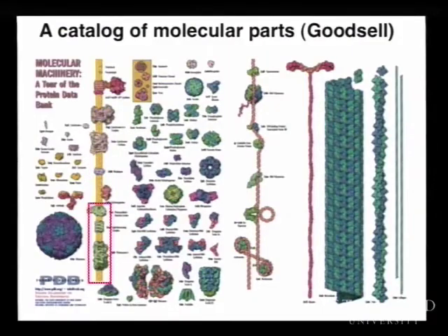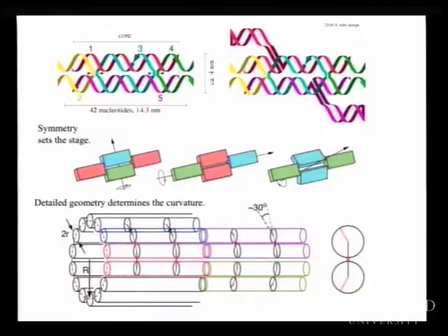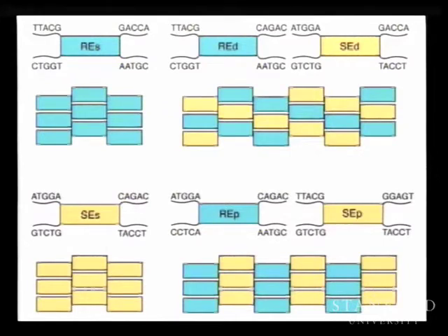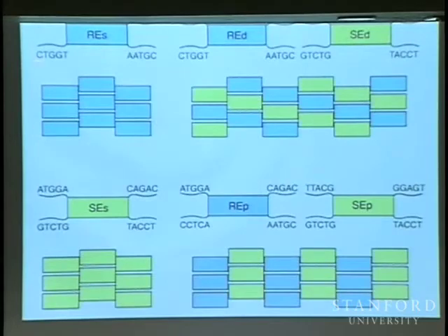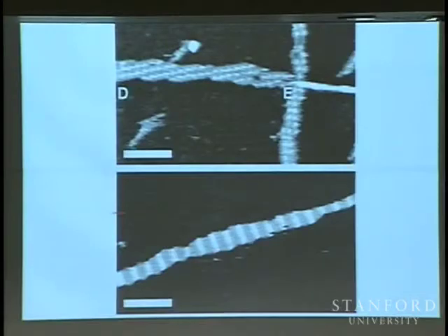This girder is made out of little protein tiles, little protein bricks. There's going to be a tube that we make out of these little DNA bricks. And so you can make different sets of these DNA bricks. For example, if you have just one DNA brick with certain DNA sequences hanging off its corners, it can make a uniform 2D lattice. If you use two kinds of bricks with different so-called sticky ends of DNA sequences, you can make a diagonal pattern, you can make a stripe pattern. And when you look at them under an atomic force microscope, and I'll talk a lot more about this later, you can see that you can actually make these molecular structures in a programmatic way from these little bricks.